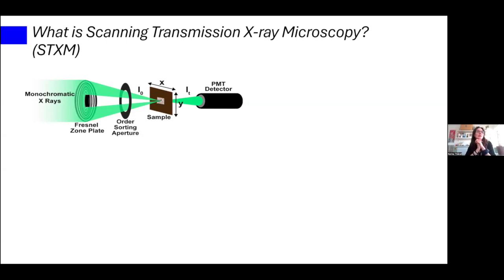In the end station, what we have is a focal element called a Fresnel zone plate. They are very small. On average, they have a diameter of 300 micron. They are usually made of gold, or sometimes nickel or other materials, iridium, in small circles with raised profiles on them. What they do is they focus the beam, they diffract the beam into a small spot.